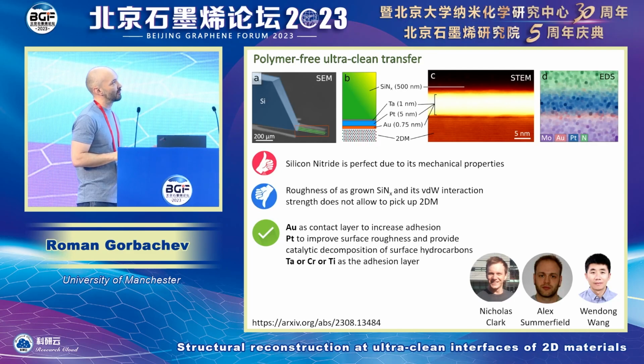What you do, you deposit a thin layer of metals, 3 different layers, 3 different metals. Again, I'm not going to go into detail why we do this, but gold here is the key. Gold is the glue that picks up the materials, and by controlling the thickness of gold, you can control the adhesion between 2D materials and this membrane. So if you put, for example, 0.1 nanometer, nothing will stick. If you put 1 nanometer, everything will stick, but then you cannot get it off.